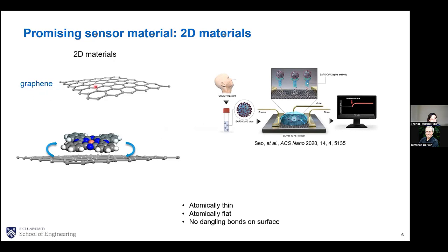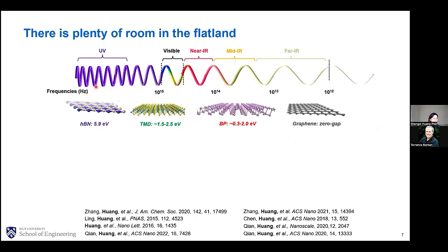So basically, these 2D materials will have no dangling bonds on their surface, making sure we will achieve very low noise in the sensing signals. And of course, beyond graphene, we have many types of 2D materials in the flatlands. For example, graphene is sitting over here. And in the UV range, we have hexagonal boron nitride, which will be very important for UV applications.